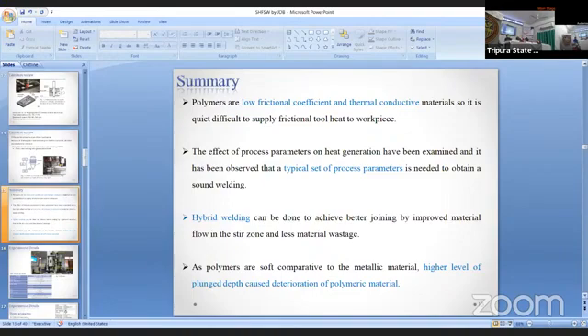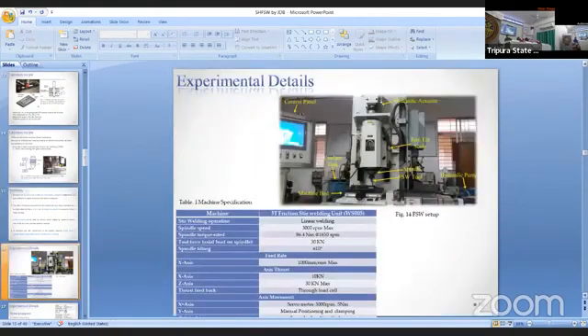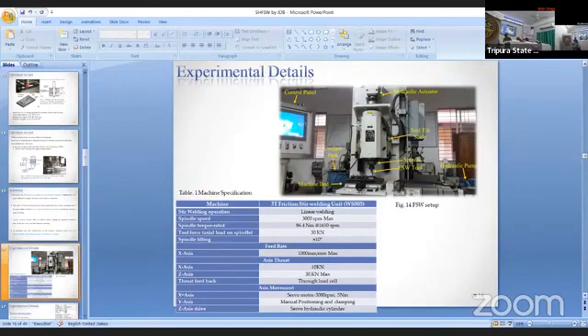So, for example, whenever we particularly talk about friction stir welding of metals, we can go for higher level of plunge depth because that ensures the forging of the materials, and which also involves better mixing of the materials. But in case of polymeric material, this is not possible because polymeric materials are soft. So that is the problem. That's why the idea of developing the tool came up in our mind. So this is the machine which is present at NIT Agartala, where we have performed the experiments. And this is a 3-ton friction stir welding setup.